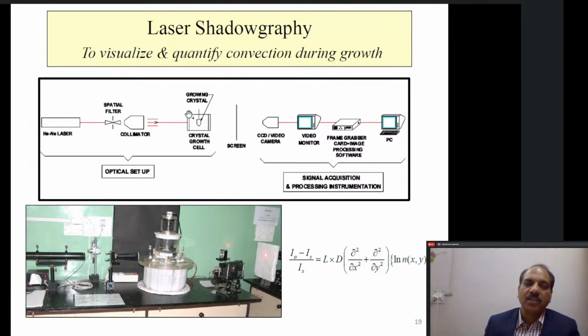These are specially designed because you have to have flat windows on both ends, because the laser has to pass through. If there is a curvature, then these two ends will behave as lenses, which we do not want. We don't want the ends of the crystal growth chamber to behave as lenses. We want the beam to fall on flat faces, with the crystal growing inside. So whatever image you see on the screen is actually the information of the concentration as well as the flow fields inside the crystallizer. The images will show you what beautiful images we were able to see. And finally, we have the signal acquisition and data processing instrumentation. We have a CCD camera or a video camera in which we continuously record the experimental images, and then there is a video monitor, a frame grabber card, image processing software, and finally a PC.